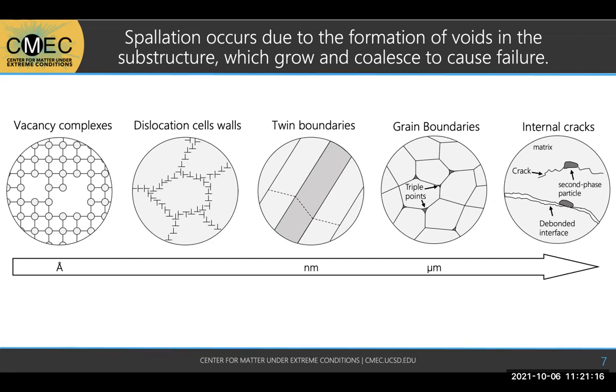And at the largest length scales, obviously, if you have a not so perfect metal crystal, and you have larger particles or inclusions or precipitates, those can actually cause cracks to form and start opening up the structure. Next slide.